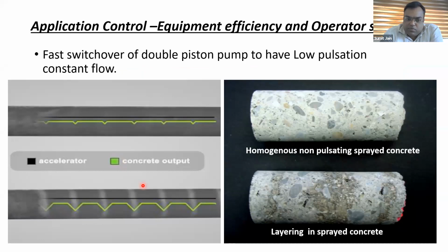Now, as Davide discussed last time, he showed you an image where two pistons were going up and down to push the concrete into the nozzle. So there is a double acting piston in which the concrete is getting pushed. And when the piston changes from one to the other, there is a sudden drop in the flow of concrete, whereas there is no drop in the flow of accelerator, because accelerator is added at the nozzle through a separate pump, but concrete is added through a different double acting piston pump. So there is a drop in the concrete and there is no drop in the accelerator.